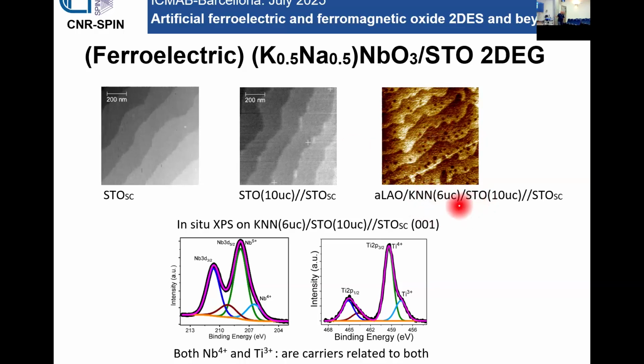I just would like to point out the in situ XPS shows the formation of, so the transfer of electrons, not only in titanium 3d states, titanium 3+, but also the presence of some niobium 4+. So in principle, also electrons are transferred in niobium 4d states. Of course, we don't know at the moment if these niobium 4d electrons contribute to the transport. But I mean, this is what we obtained from XPS analysis.